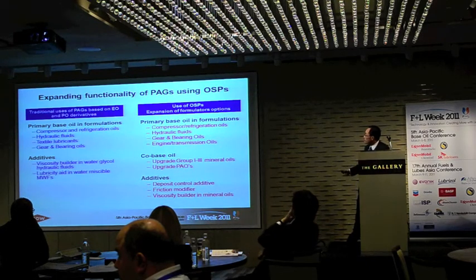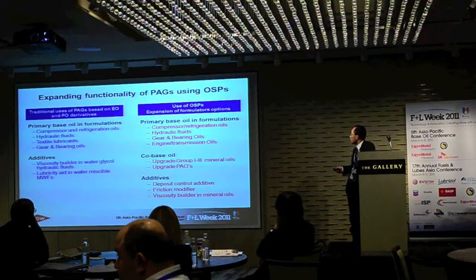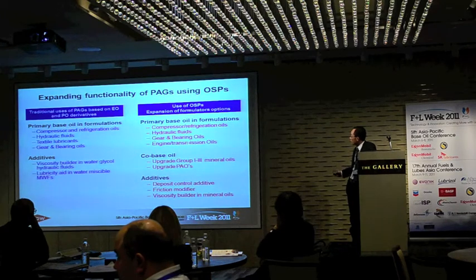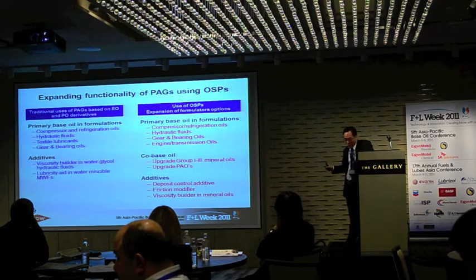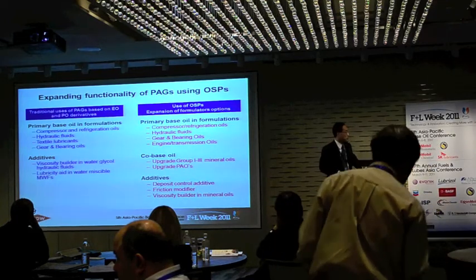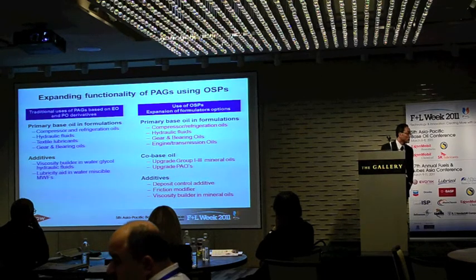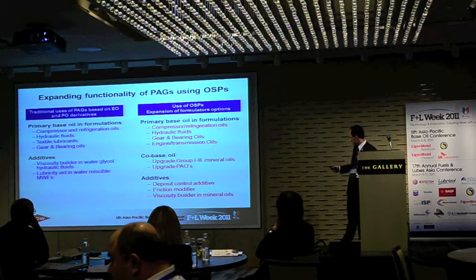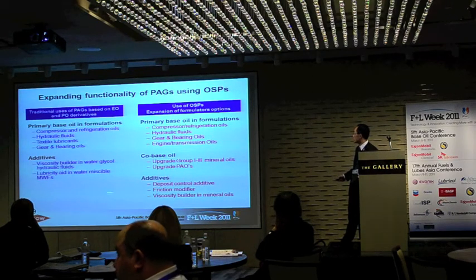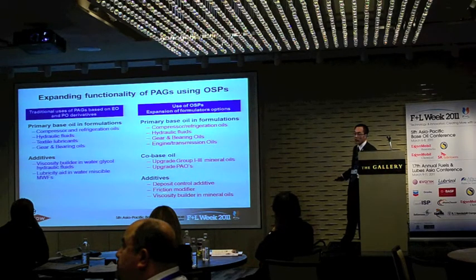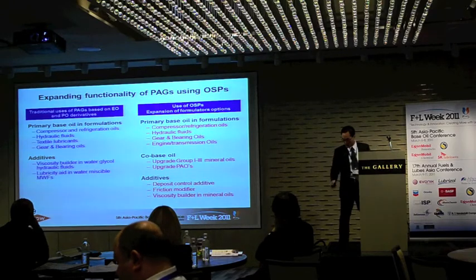If you look at the OSPs, by having this new oil-soluble polymer, you can see that not only can you use it as a primary base oil — we are also designing this one as a co-base oil. You can see by having this OSP either in the mineral oil or in the PAG-based oil, how this OSP can help you make your performance a little bit better. As an additive, this can give you the same function as the traditional PAG in terms of deposit control, and definitely the high-viscosity oil you can use as a viscosity index booster in your formulation.